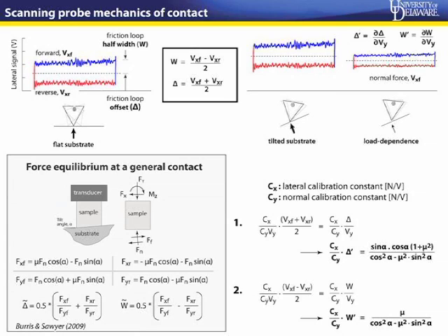Now, if instead of a flat substrate, we use a tilted substrate and load the AFM tip, you'll notice that the normal force that is being applied at the interface now does not pass through the shear center of the cantilever. What that means is you will have some finite initial moment, which shows up as the deflection of the offset from the flat substrate center line. And then once you start translating back and forth on the tilted substrate, if you're applying the same normal force, you will end up with a friction loop which has now been shifted up because of the tilt of the substrate. If you were to change loads on a tilted substrate, you would be changing both the delta, or the loop offset, and the loop half width. Why that happens is, clearly, if you're changing load, you're changing friction, so that would change your W.